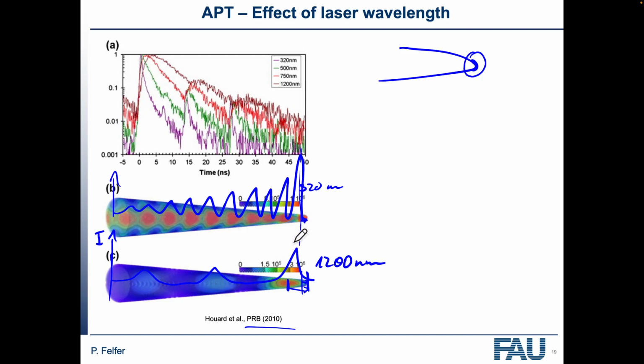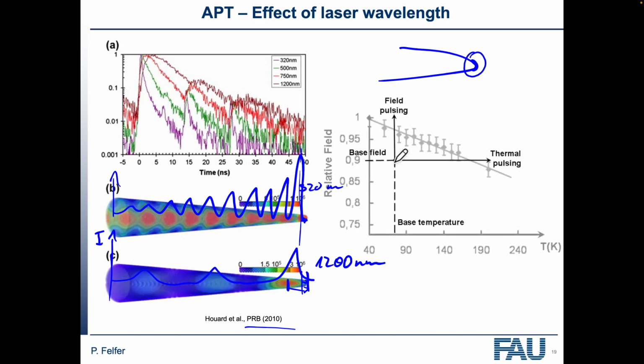This, of course, really all just is on the basis of these very few papers. And some people that do laser physics have very different opinions and say, okay, maybe you oversimplified your problem here. So on our laser, we will have the ability to choose between the fundamental, which is infrared, the second harmonic, which is green, and the fourth harmonic, which is 260 nanometers roughly. We don't have the third one because you only get 3 ports in this case. And so we can try out if it really is just this wisdom here, or if there's a little bit more to the story. Because of course, different materials also absorb differently, and these simulations are for metals, for ideal metals.